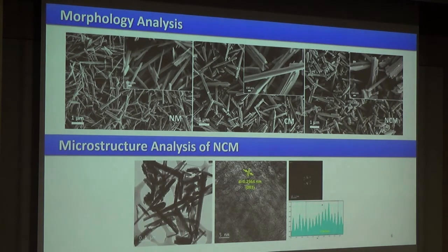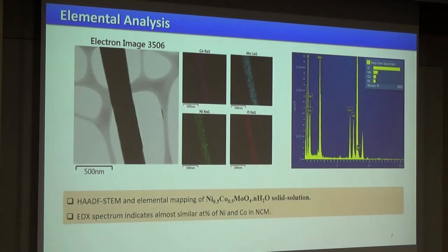Now the microstructure analysis of NCM shows that growth of the 003 plane was observed, and the spot-like selected area diffraction pattern also indicates its good crystallinity. Further, the elemental analysis of this material was carried out through HAADF-STEM and EDX, and it shows the presence of its constituent elements.